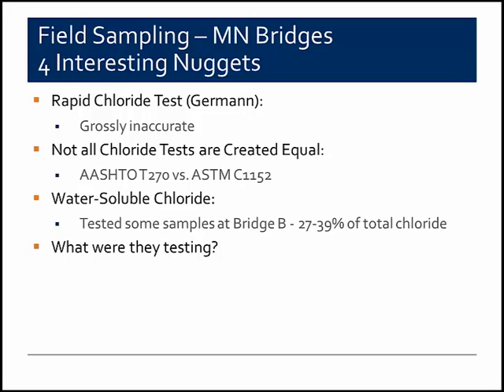And so there was some back and forth on what the appropriate test to run was because of that. And one of the convincing factors was that PTI, ACI, and even AASHTO all recommend ASTM C1152 as the proper test for performing acid-soluble chloride content testing.